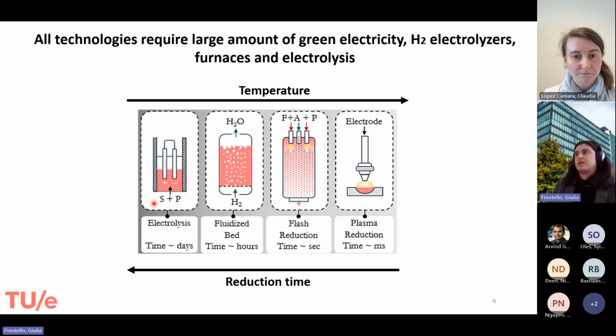If we look at all these technologies, of course, there are pros and cons, and we will have a look at these pros and cons for all these technologies. What you see here is that these technologies are put in perspective for increasing time. If you decrease the time, your reduction rate increases. So you can do reduction faster. You see here that we pass from reduction times of days to milliseconds, so the reduction time is decreased a lot.